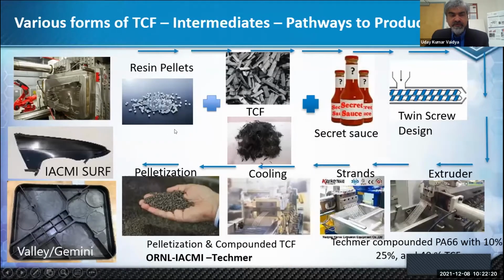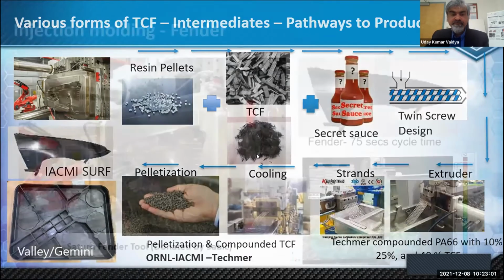Coming to some of the discontinuous forms here. TCF has of course been extensively looked at in pellet form with a range of resins, including polypropylene, PA6, PA66, etc., going through the pelletization step. And then in the IACMI SURF facility in Michigan, that is a scale-up research facility, using large-scale injection molding, like 3,500-ton injection molding with actual automotive tools. This is a quarter fender here, produced with this textile fiber polypropylene, as well as other representative components. So completing this cycle has been effectively demonstrated.